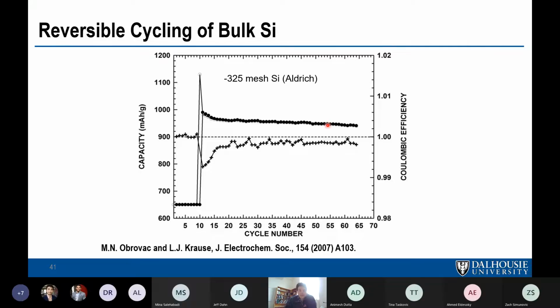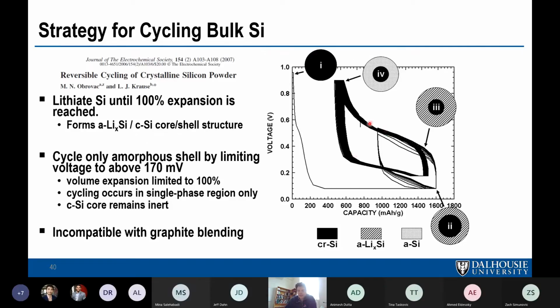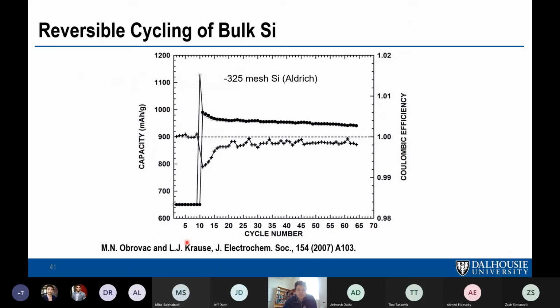The problem with this is, if you're limiting the voltage up here, the average voltage is high, which reduces the energy density. And another thing is, as we'll discuss later on, to get good electrode density, you don't want porosity in your electrodes. These things have to be calendered, and to get good calendered density, you need to add graphite. And if you're adding graphite, you should cycle the graphite because you don't want it to be empty or dead space in your electrode. And so you have to go below 170 millivolts to cycle the graphite. So this is not compatible with graphite blending, as it says on the bottom of the slide. So that was an issue with this kind of strategy.